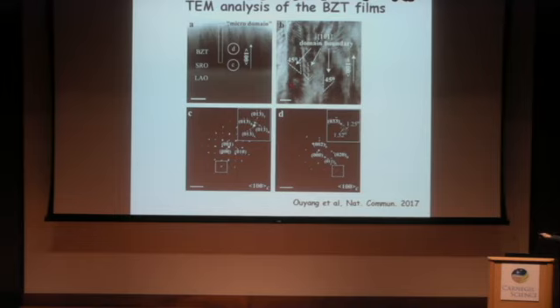And then we did some selected area diffraction work. Near the interface, that's the circle C, of course we found the substrate, we found the bottom electrode, and we also found tetragonal and rhombohedral spots. And when you go more into the film bulk, which is D here, you can see the tetragonal spots disappeared, but you have some very fine structure in the rhombohedral diffraction spots. And eventually, we figured out this is because you have two sets of rhombohedral microdomains, which grow from the bottom interface up until the surface of the film.